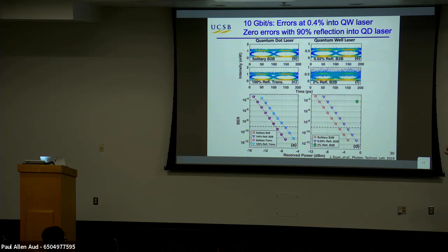There's no change in bit error rate at all. This is if you put it through fiber just to see if there's a transmission effect. So back-to-back is the squares, and 100% reflection is the triangles. So again, no effect. So you really don't need an isolator for a quantum dot laser. That's the point, if you make them uniform enough.